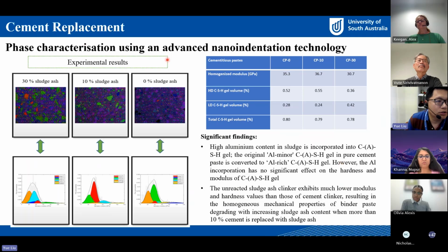This is the result for the nano-indentation test. For the nano-indentation test, we combine the traditional indentation test with EDS mapping. That links the mechanical response of each spot with its in-situ chemical analysis.